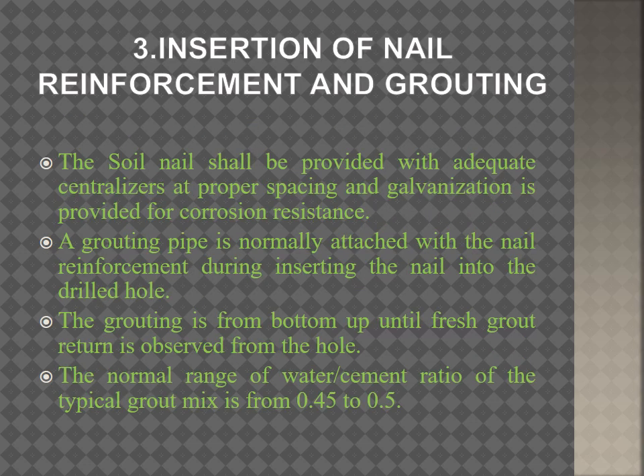Step three is insertion of nail, reinforcement, and grouting. The soil nail shall be provided with adequate centralizers at proper spacing, and galvanization is provided for protection against corrosion. A grouting pipe is normally attached with the nail reinforcement during insertion into the drilled hole. Grouting proceeds from the bottom up until fresh grout returns from the hole. The typical water-cement ratio of the grout mix is 0.45 to 0.5.